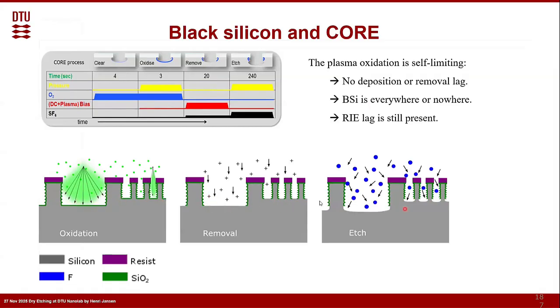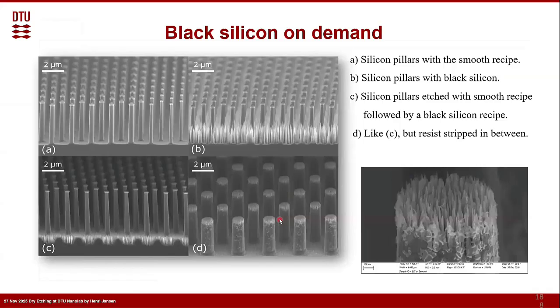So either you have cleaned both of them and you can create a very nice directional profile without any roughness, or if something is left, it will be here, but then it would be also here, because they had the same thickness and the ions don't see the difference in the structure height, in the aspect ratio. So either everywhere grass or not. So that's why you have it. And in that way, you can tune it now very nicely. Either you put it into a mode where everything is nicely clean, or you didn't do it sufficiently and then there's grass.